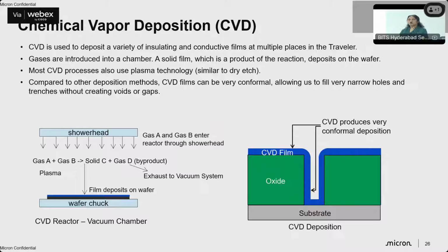Chemical vapor deposition. Now, all of these features, and we are talking about, say, an aspect ratio of 1000 to 1, are really, really deep, tiny structures. Imagine trying to fill them with a spin-on film, say, something water-like. First of all, it may not actually go inside these features, or it may have a surface tension effect taking place. That's where deposition comes into play, where it has a tendency to deposit a conformal film. So, for example, if you're trying to create really tall capacitors, how do you line them with metals? That's chemical deposition.